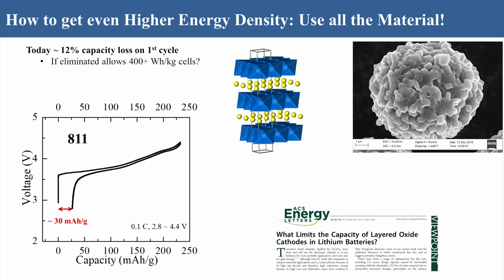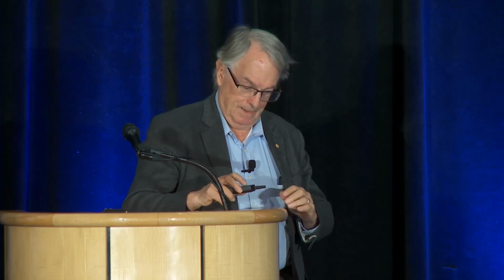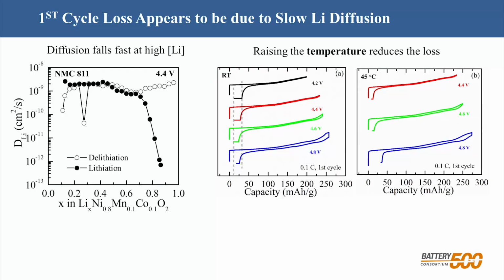So one of the issues with all these layered oxides, we lose 10 to 15% of the capacity on the very first cycle. So we can take the lithium out, we cannot get it all back in. And we wanted to understand why this is and see if we could solve it. And it's a typical thing a material scientist would do. We looked at it and said, the lithium ions must be diffusing too slowly.